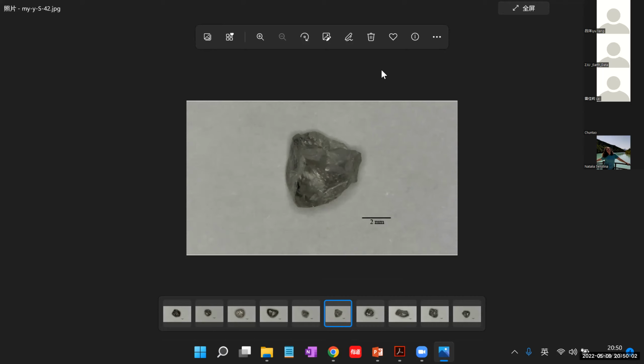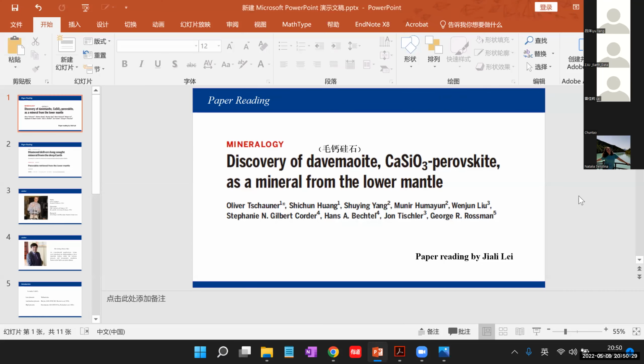It's interesting because no one has really got a real calcium perovskite from the deep. This is probably one of the first ones we have got. So people have no idea how it really looks like, and it's very rare samples too. And what people synthesize in a laboratory, even though people could synthesize different compositions, those are just synthesized ones. You don't know what the composition of real ones looks like. But it's interesting because, yeah, it could also be a pyroxene.